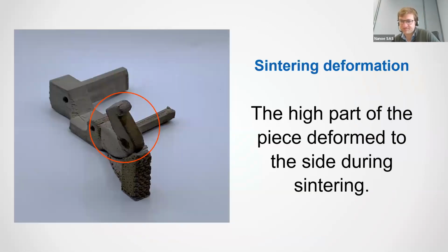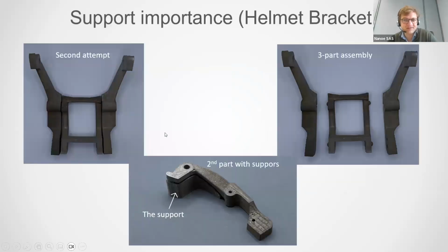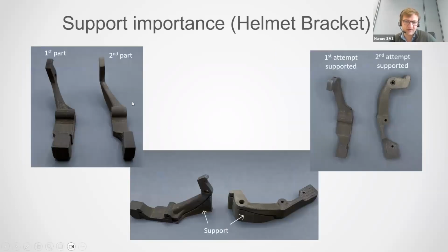The problem is this worked, but we did have some deformation because you have a part here which is relatively high. We did mention the fact that high walls can deform, and that's typically what you'll have. They just sagged on one side because of gravity during the sintering stage. So we had to rethink our approach, and we actually separated the part in three so that we could better support the bracket elements by flipping them on the side, as you can see here, which really makes for a much stronger support and avoids any high walls that can deform during sintering. You can see here how it works, and the fact that the second part had no deformation at all, while the first one had some deformation.